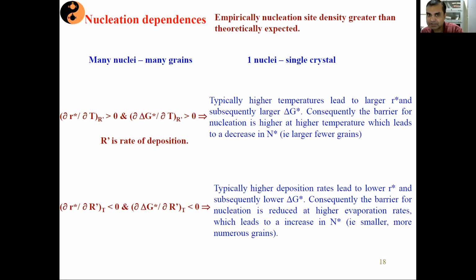If I generally compare with respect to single crystal, then single crystal is nothing but a single grain. Single grain means I will require only one nucleation site. If your substrate has many nucleation sites, then at all those nucleation sites, the growth is actually taking place, and all those growths are possibly taking place in different directions. And therefore, those films will give rise to polycrystalline films. So many nuclei means many grains, possibly polycrystalline films. That is something which we have to understand.